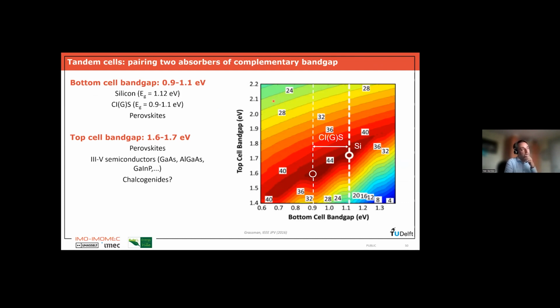This is an efficiency plot for such a tandem as a function of the top cell and the bottom cell band gap. We see that theoretically, we can reach even efficiencies up to 44%. So it's much higher than the 29% that we saw before. But you have to choose the right band gap materials. The bottom cell typically needs to have a band gap between 0.9 and 1.1 eV. That's good news because silicon has 1.1 eV, so it's a good bottom cell. And then for the top cell, you need a band gap typically of around 1.6 to 1.7 eV.